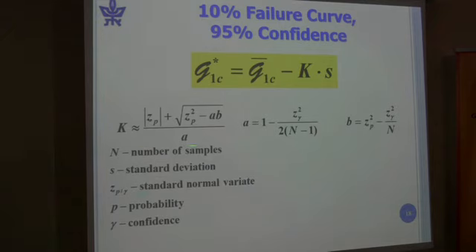So we can use these ideas in order to lower our G1C average quantity. We have the number of samples n. The standard deviation of G1C bar is S. We calculate this K factor, which depends on ZP and Z gamma. And P is the probability, and we chose a confidence of 95%. So we have a 10% probability of failure in the safe zone, with 95% confidence in our choice of that curve.